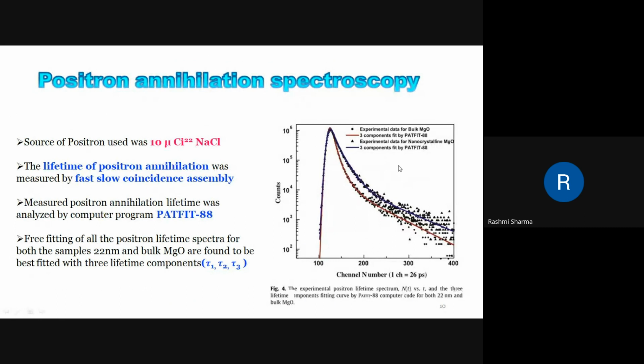Now the main technique employed was positron annihilation spectroscopy. In the process of annihilation between an electron and a positron, the positron combines with the electron to form positronium, which is a quasi-atom. When they combine, it results in the production of two gamma radiations, each of energy 511 kilo electron volt. The source of positron used was a 10 microcurie 22NaCl source. This source emits positrons.